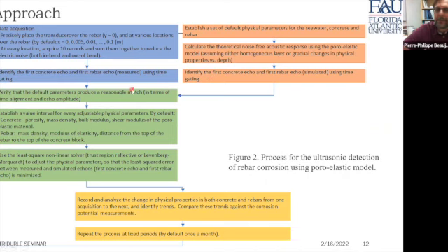Now, the next thing we do, we combine model and measurement to verify that the default parameters produce a reasonable match in terms of time alignment, and amplitude of the echo at the concrete surface and in the rebar. And we establish a value interval for every adjustable physical parameter. By default, these parameters will be, in the concrete, the porosity, mass density, bulk modulus, and shear modulus of the poro-elastic material. In the rebar, it would be the mass density, modulus of elasticity, and the distance from the top of the rebar to the bottom of the concrete block.